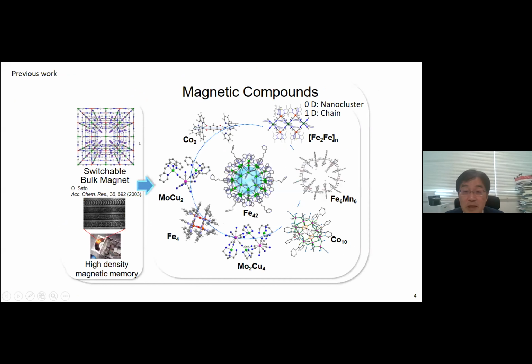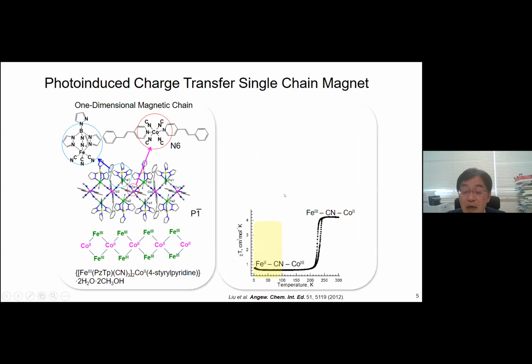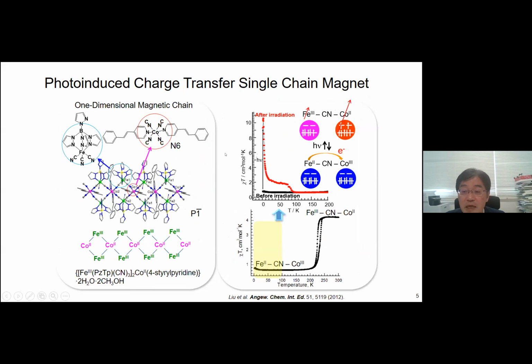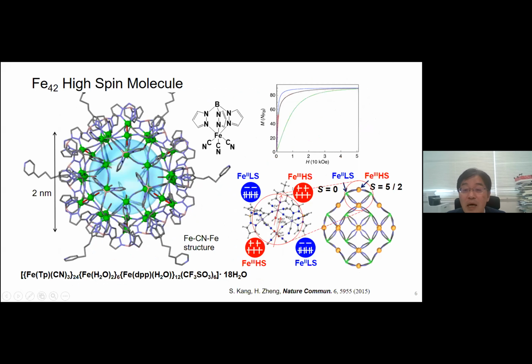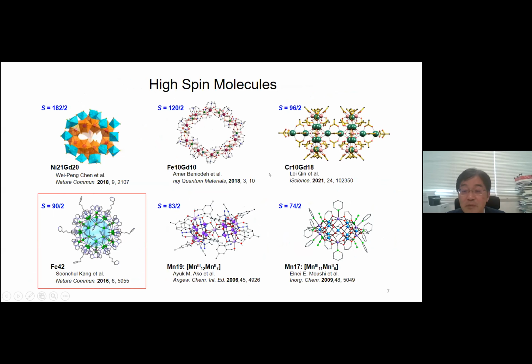And previously, we reported several magnetic compounds and switchable magnetic compounds. And one example is shown here. We reported an electron transfer iron cobalt complex. This complex exhibits electron transfer by temperature change and photoirradiation. And after photoirradiation, this complex exhibits a single chain magnet behavior. And we also reported high-spin molecules where iron 3 high-spin states interact ferromagnetically, forming a high-spin state S equal 90/2. This is one of the largest high-spin molecules reported thus far.